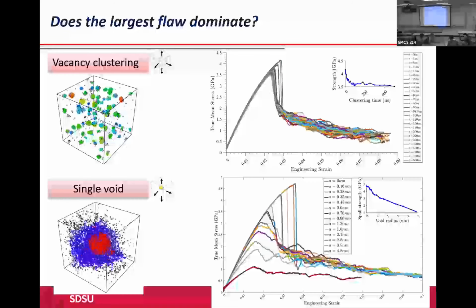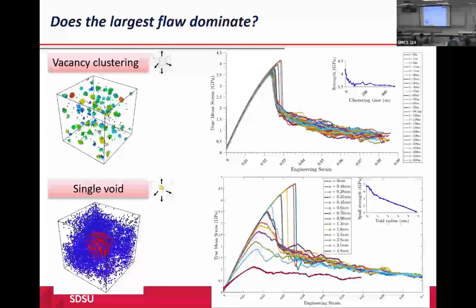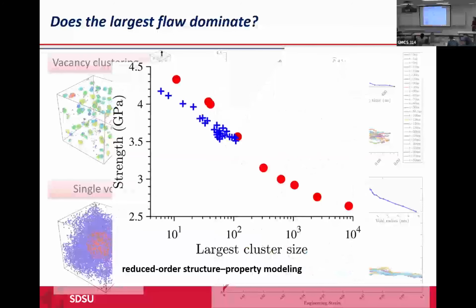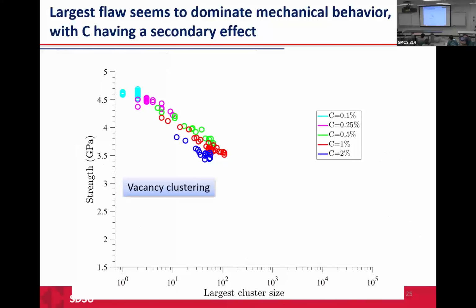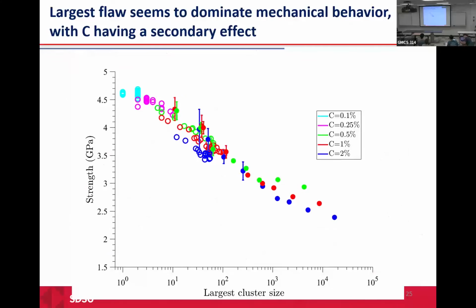We got the stress strain data for both of them, and then we put those data on the same curve. And basically, they can match a little bit. I mean, in most areas, they can match in a good sense if we want to build up a model based on the larger cluster size. Then we used these data, we are trying to develop a continuum-based type of model and improve the model that we have.